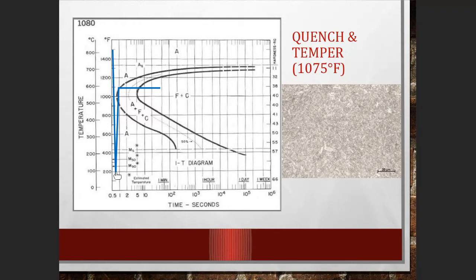Now, your tempering temperature will define how, I guess you can say, undistinguished your needles become. The lower your tempering temperature, so if I were to go right above the martensitic start temperature for tempering, I would still have some designation of defined needles. But because I was at higher temperature, I soften the material more, diffusion's allowed to occur, so the distinguished needle structure kind of disappears, giving you this type of morphology.